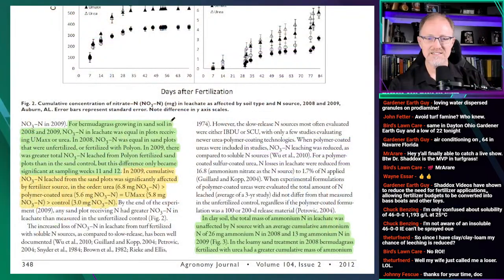Let's continue. For Bermuda grass grown in sand soil in 2008-2009, nitrate in leachate was equal in plots receiving UMaxx or urea. So you said it again. In 2008, nitrate was equal in sand plots that were unfertilized or fertilized with Polyon. So the polymer coat is resulting in basically background levels. In 2009, there was greater total nitrate leached from Polyon-fertilized sand plots than in the sand control, but this difference only became significant at sampling weeks 11 and 12.